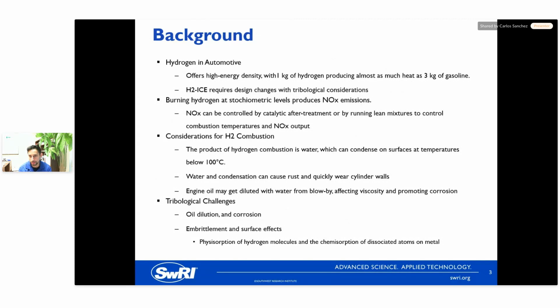As far as hydrogen combustion goes, one of the other considerations is that hydrogen produces water as one of the byproducts, which can condense on different surfaces at low temperatures, anything below 100 degrees C. Of course, water in any mechanical system that has a lot of metallic components can cause rust and premature wear in different areas, especially in cylinder walls. In addition, the water from the blow-by can dilute engine oil and other lubricants, which affects viscosity and also promotes corrosion. So again, the tribological challenges would be oil dilution and corrosion, and of course the embrittlement related to hydrogen absorption in the surface.